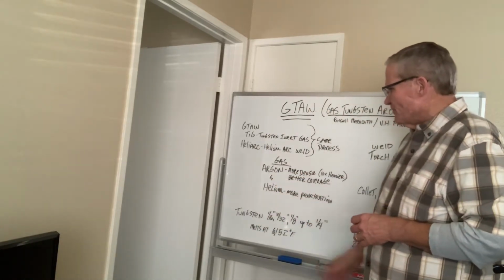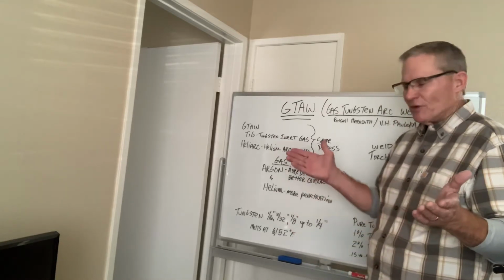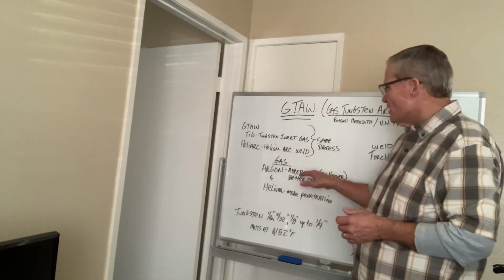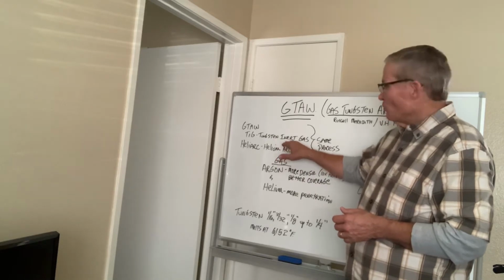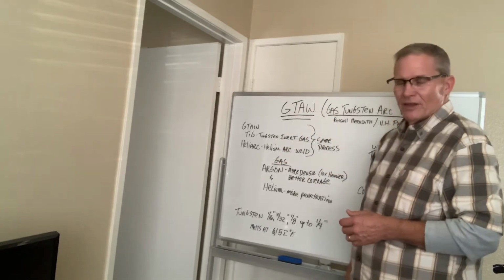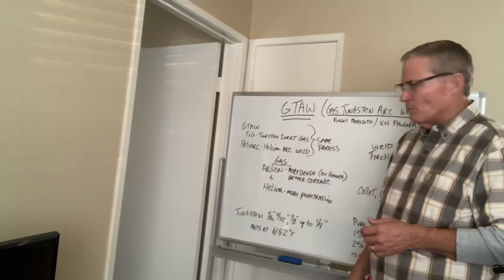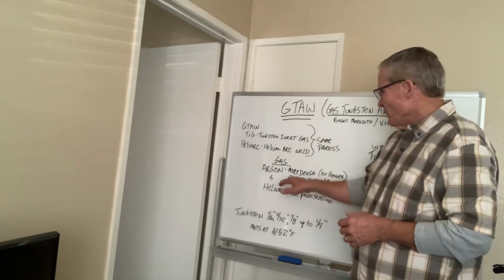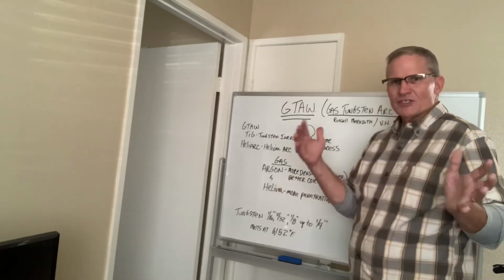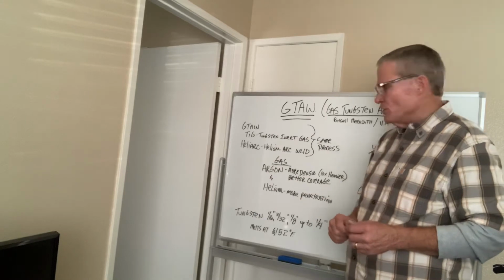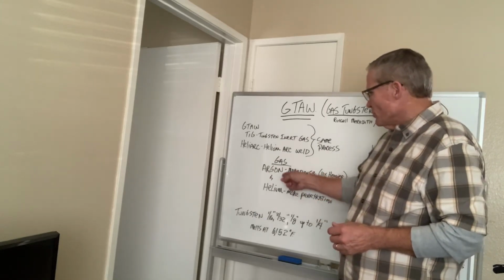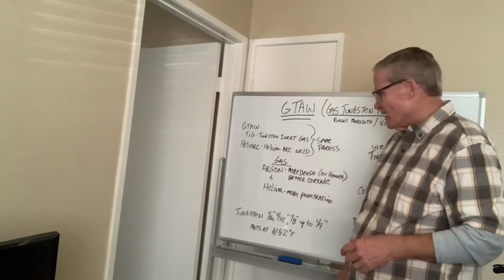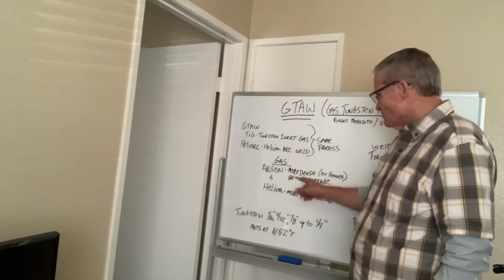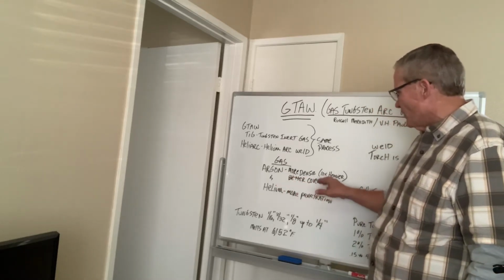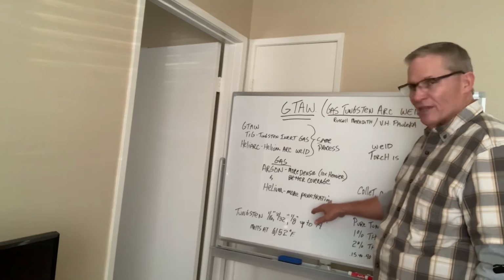These are definitely the most common. There's other gases that are used, and there's gases that are not inert, which is why we have another formal name for this welding process. But in the grand scheme of things, most of the welding that you do with this process, you're either using argon or helium as the backing gas. The argon gas is more dense and you get better coverage with it. It's actually heavier than the helium.